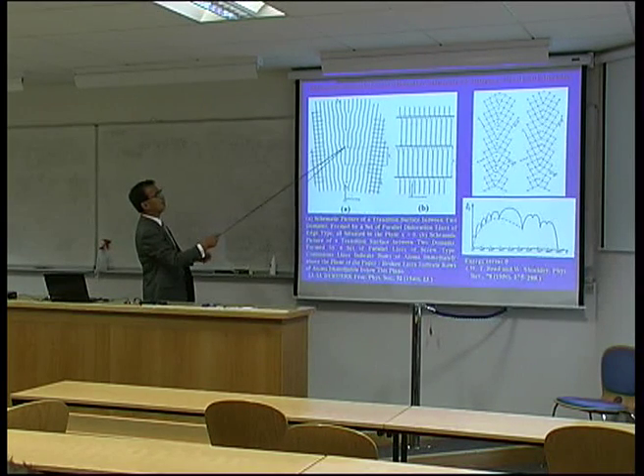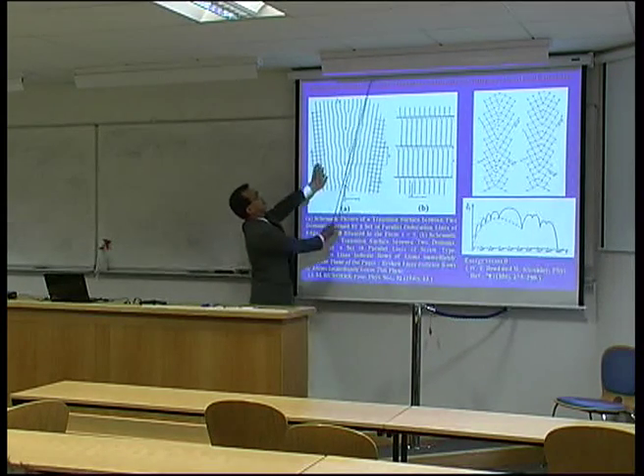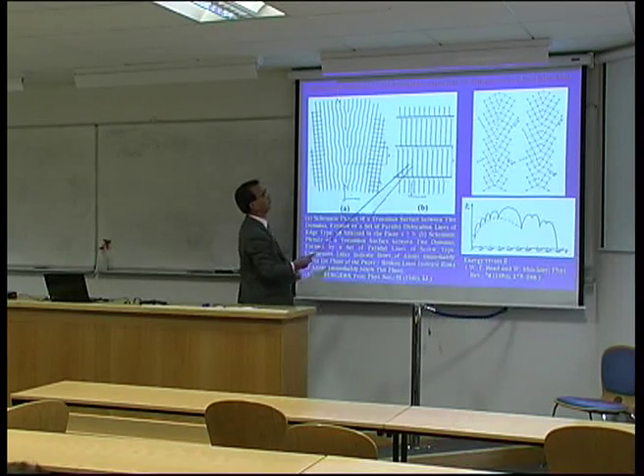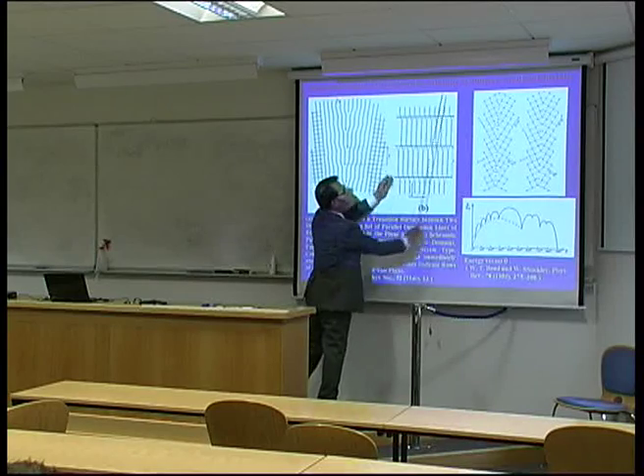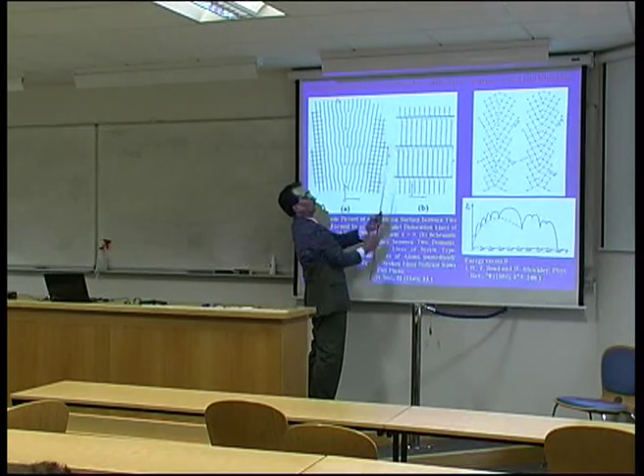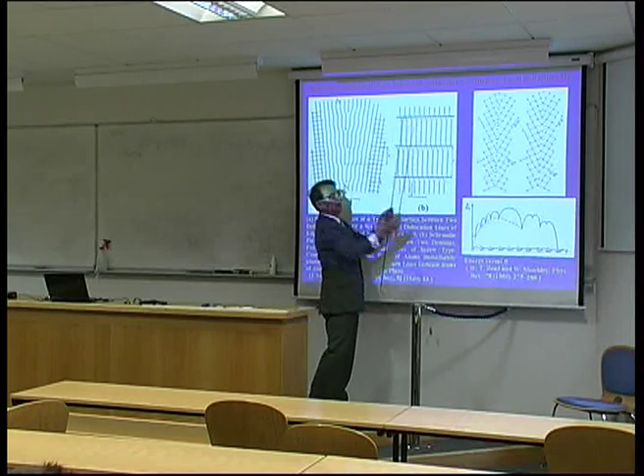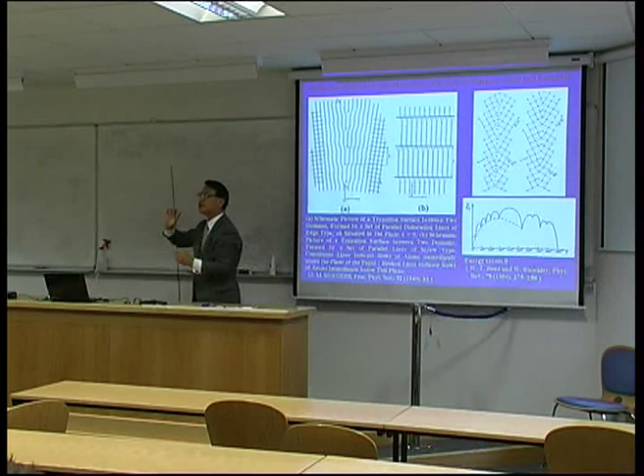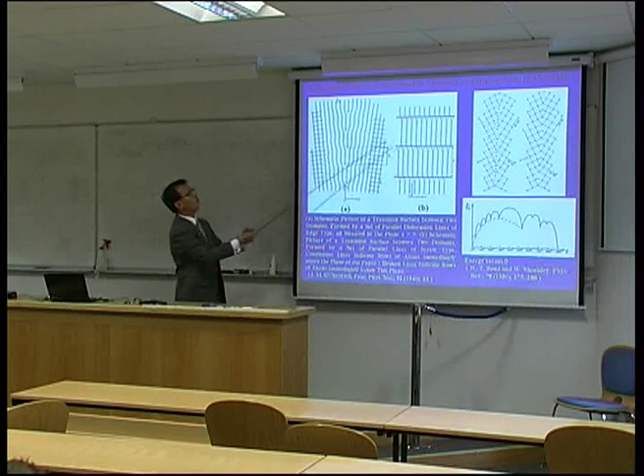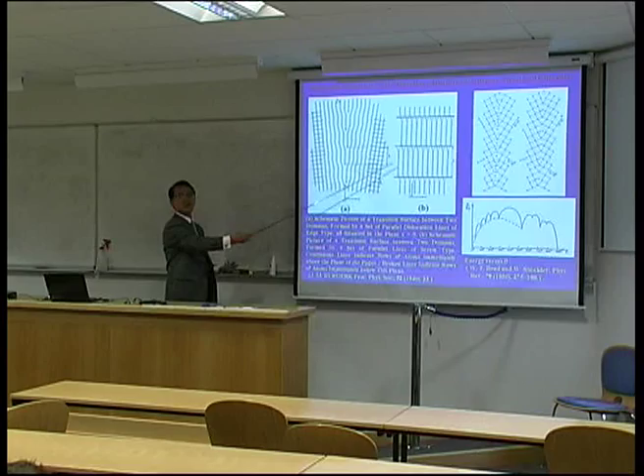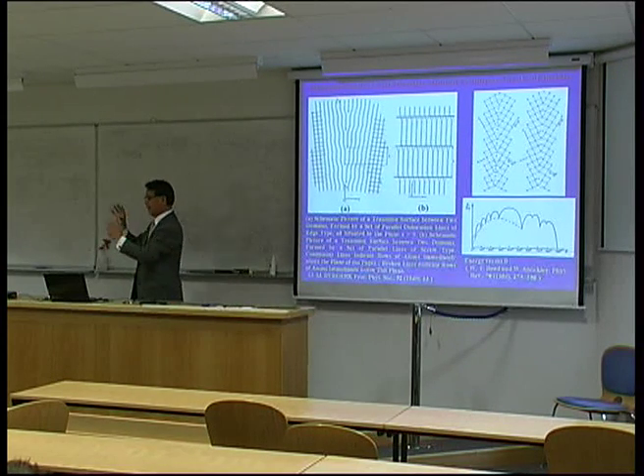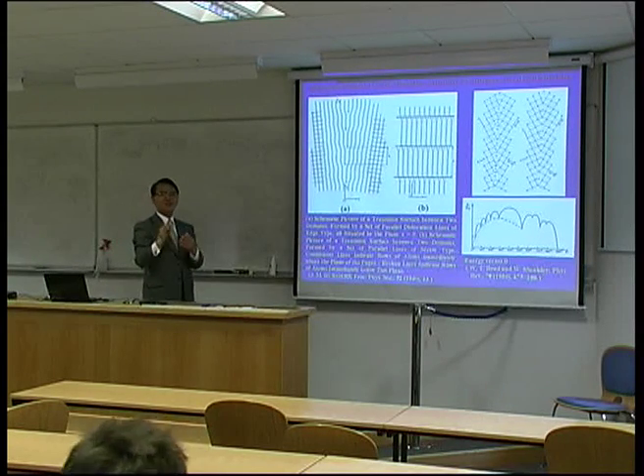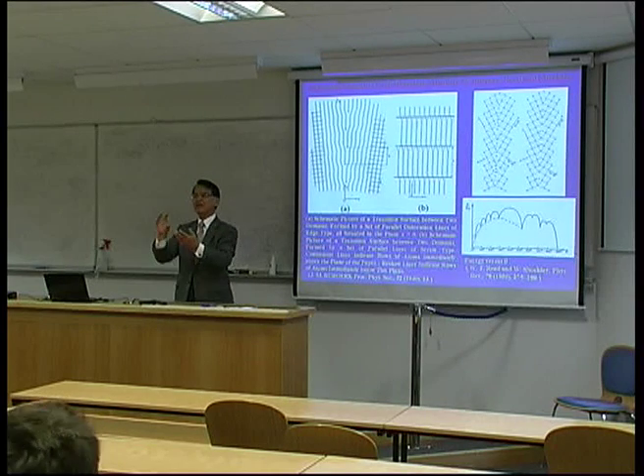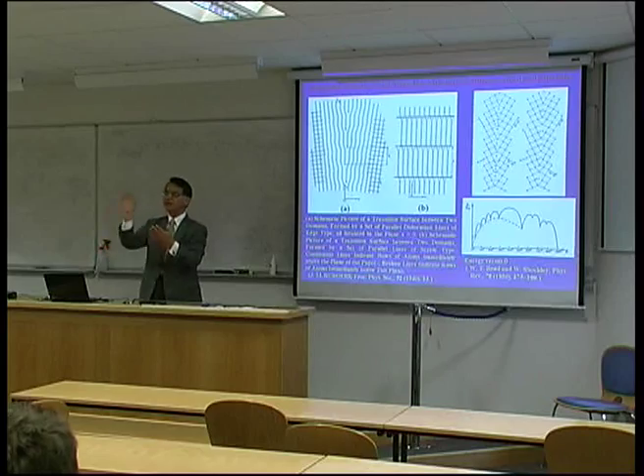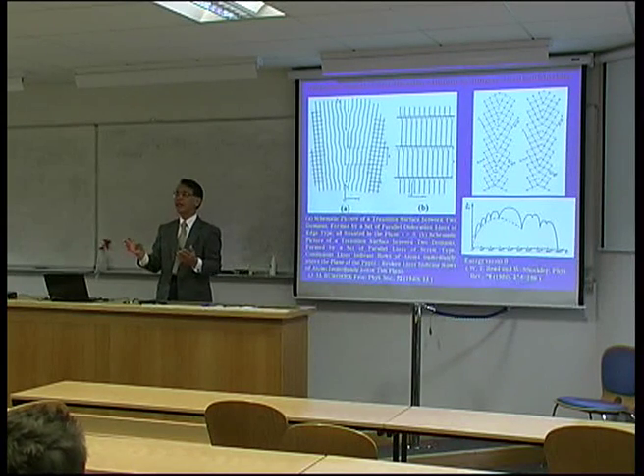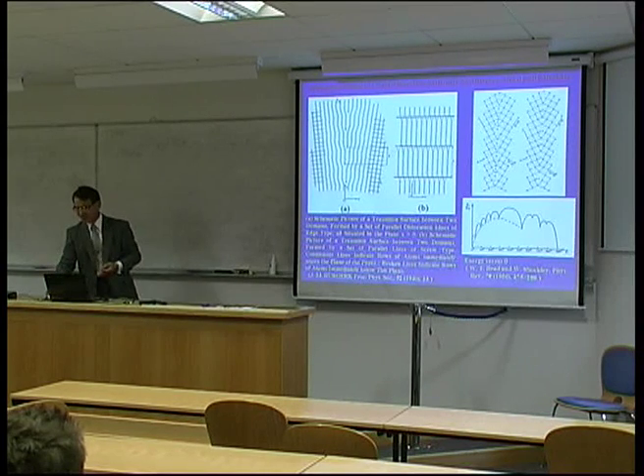If you put edge dislocations like this, we can form a tilt boundary like this. If you put screw dislocations like this, like a network, we can rotate the two crystals below and above the screen, just twist like this, so we can form a twist boundary. So by introducing edge or screw dislocations, we can construct a tilt boundary or twist boundary. But again, in a real boundary, a pure tilt or pure twist does not always occur, but they sometimes are of mixed type, which has a tilt component and a twist component, and this can occur very normally. So the situation is rather complicated, but anyway, we can think about it.